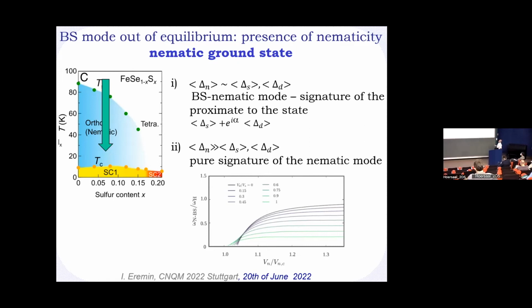But what is more interesting is the situation when you have a nematic order parameter which is completely dominating the superconducting state, so that means that you have a delta nematic which is larger than the expectation value of the s-wave and d-wave components. Then you will see that the mode becomes stiffer and essentially acquires all the polarization dependence which comes from the nematicity. And this is where you can conclude that what you probe in the superconducting state is not just a Bardasis-Schrieffer mode, but essentially a nematic mode with a corresponding polarization dependence.